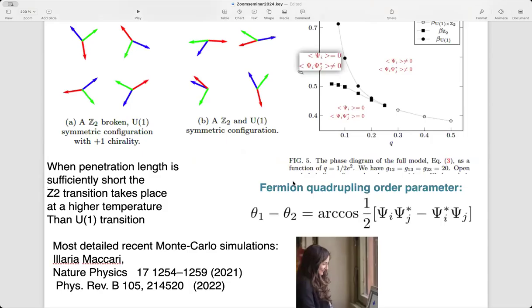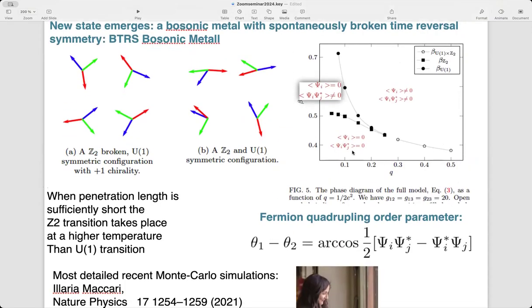And then let me just show the simulation, the Monte Carlo study of the phase diagram of this model as a function of, basically, Q, the inverse gauge field coupling constant. So essentially, it parameterizes the magnetic field penetration length, and then one finds three phases. This corner corresponds to high temperature. So at high temperature, small beta, the system is completely disordered. Of course there is the Elitzur theorem.